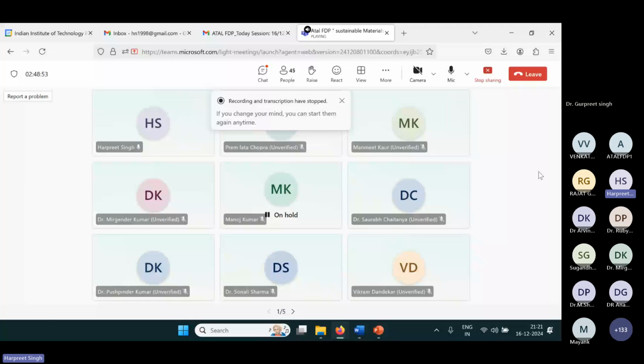One thing. Second is, we now have a lot of database for these temperature settings, or what you call process parameters, for different types of materials, right? So you have to refer to that. For example, it will depend. If you are trying to deposit nickel chromium alloy powder, you will get a lot of data on what kind of pressure and these parameters of say HVOF or detonation gun or thermal spray has to be fixed. But if the material is entirely new to you, then only two things can help.